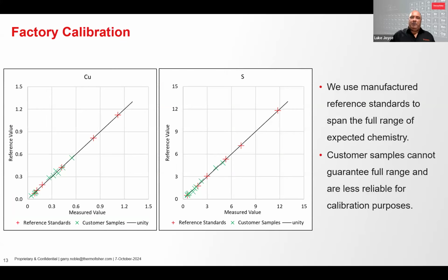So we use manufactured reference standards to ensure the full range of chemistry is fully spanned. Experience has taught us that it's very difficult to obtain customer material samples that span the full range of every element, and using such samples would compromise the calibration. These plots show the copper and sulfur ranges for the manufactured reference standards, shown here with the red plus symbol, compared to the narrower range samples we obtained from Newcrest, shown here with the green crosses. These were measured during the factory calibration of the CB Omni analyzer we supplied to Red Chris, which was installed in 2023.